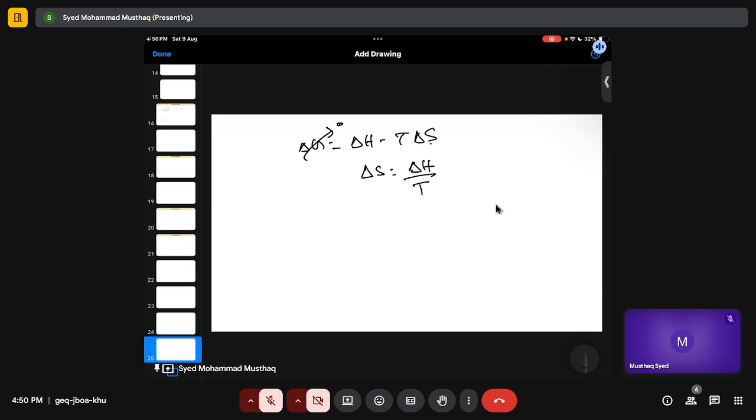And you substitute here. So xv will be equal to, all you have to do is substitute here, then exponential minus delta h upon kBT. If I am talking about per atom, I have to write it in terms of per atom. If I am talking of per mole, then it will be RT, universal gas constant times T. Okay, so we have arrived at this.